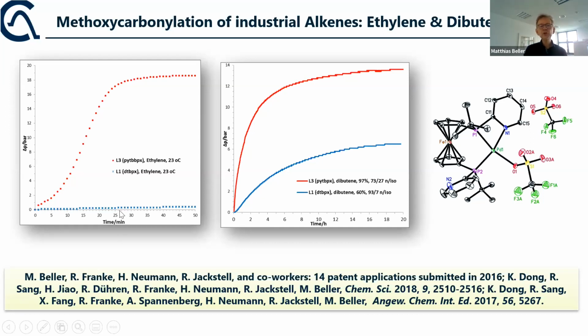So this is the methoxycarbonylation of ethylene. In an industrial setup, of course, it's not done at room temperature, but we did it at room temperature in order to show the difference more clearly. You see the activity of the pyridyl substituted pytbpx ligand is much, much higher. So this ligand also allows complete conversion, more than 97% conversion of dibutene, while the classical Lucite ligand only allows 60% conversion of the dibutene.